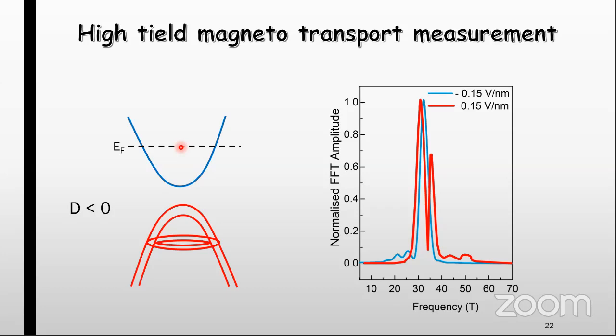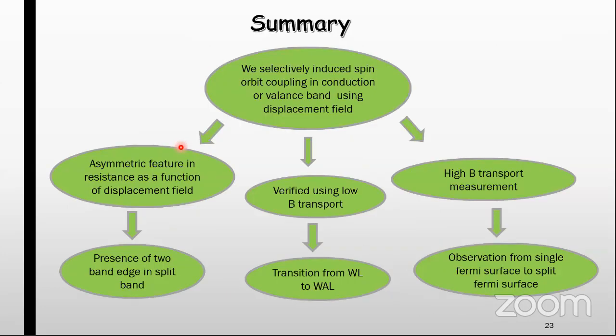So now I would like to summarize. We selectively induced spin orbit coupling in the chosen band by using an external applied electric field, which was also reflected in the asymmetric feature in the resistance as a function of displacement field, and that tells the presence of two band edges in the split band.